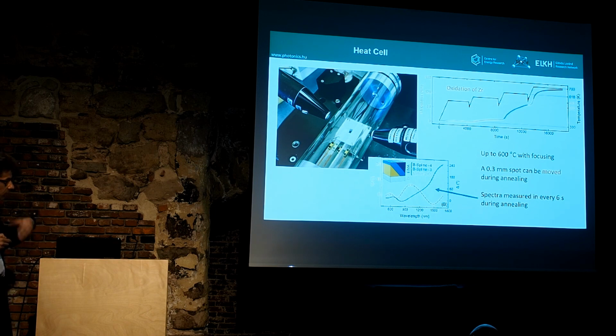And if you evaluate spectra like this, these are 1 point in this graph, this time-dependent measurement. So each point here is 1,400 data points and fitted. And from this fit, you can determine the thickness. And you can follow the change of the thickness as a function of time. But you not only have the thickness, because you can use a complex model with many parameters. And you can also have the refractive index, volume fraction, inhomogeneity, roughness, a lot of information in each second. So this is also an opportunity that you can heat up a sample, and you can in situ have an insight with a below-nanometer thickness resolution, a 1 second time resolution, and the refractive index resolution is 10^-4, so you can see a lot very quickly, non-destructively, and you can follow processes very well.